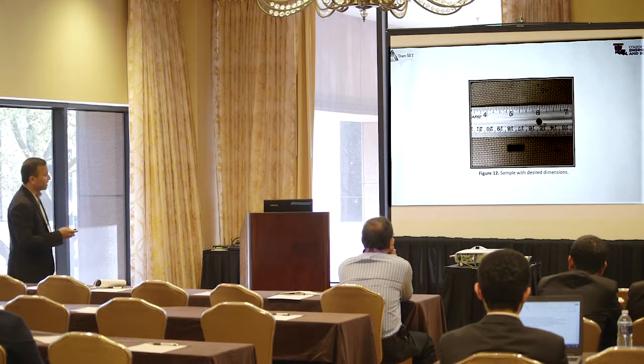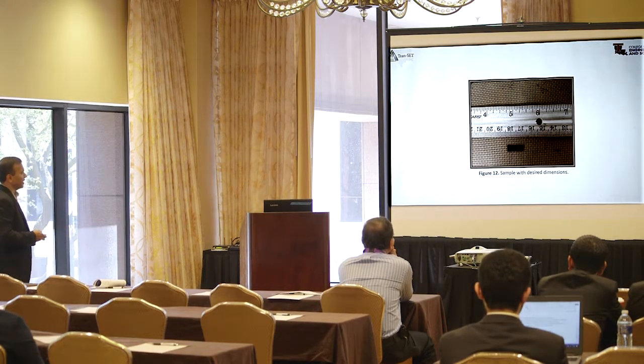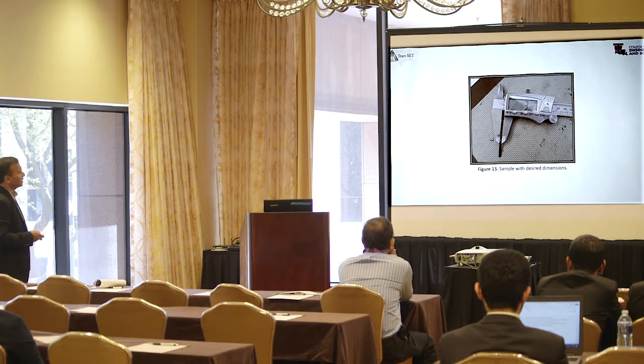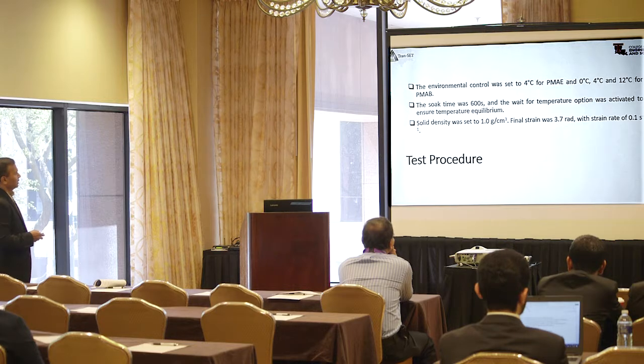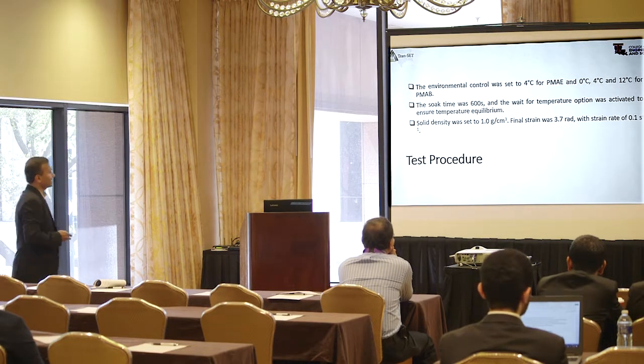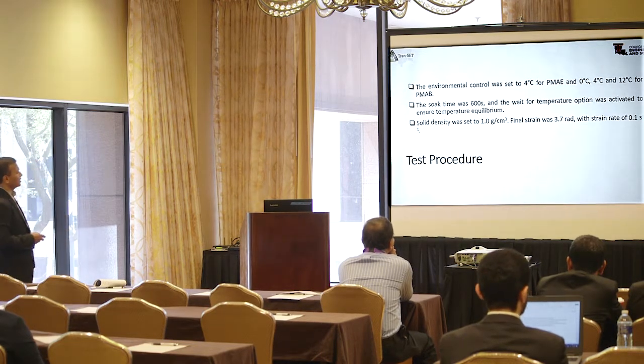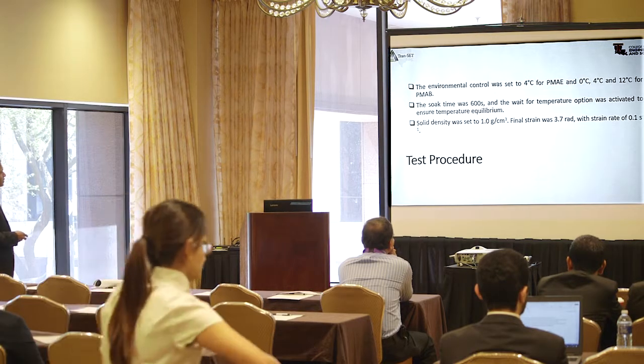But the thickness and the width you have to do manually, and that's still the critical process we're trying to maintain. Sample with desired dimensions, and then you can see that the thickness has been maintained at 3.0. So this is the test procedure after sample preparation. This is how we prepared the sample, as you see.